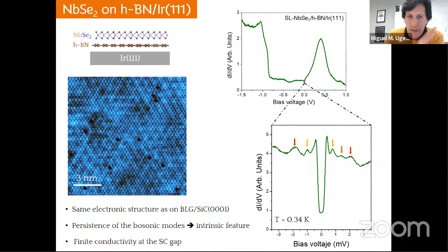The only difference between this case and the previous one is that for some reason with graphene, we see a zero conductance in the superconducting gap. And it's not the case on BN. On iridium, we believe that iridium is somehow overlapping, or we are tunneling as well to the iridium substrate.